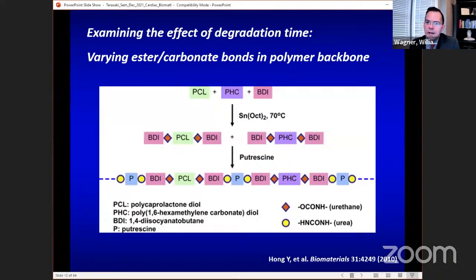So one fundamental question was degradation time. We use polyester urethane urea with polycaprolactone soft segment. It's fairly easy to play with that chemistry, as I said before, and replace the caprolactone with hexamethylene carbonate. So ester versus carbonate. Carbonate degrades slower than ester by hydrolysis. And we did some subcutaneous rat implants and showed that we could get a very nice predictable rate of degradation change as we increase the carbonate content. More carbonate, 100% carbonate, slow. Caprolactone, fast, relatively. So we had this knob that we could tune the degradation rate.